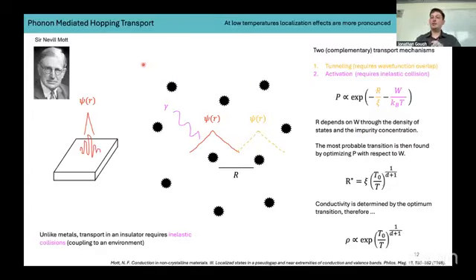So at high temperatures, I mentioned that inelastic scattering essentially breaks up localization. However, at low temperatures, when the bath energy becomes comparable with the energy level spacing of your discrete disorder states, you start to notice these localization effects. Hence why we perform these measurements at ultra low temperatures within a dilution refrigerator.